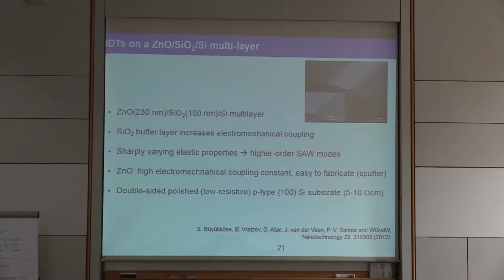So we like to combine surface acoustic waves with silicon substrates. And there you have your problem, because silicon, as you know, is not piezoelectric. You can, of course, take advantage of the deformation potential, but that modulation is much smaller. So what we need to do is to fabricate a piezoelectric layer, at least at the site where we want to generate the surface acoustic wave and also where we want to detect them. And if you need the piezoelectric potential also at your device of interest, you would also need your piezoelectric there.